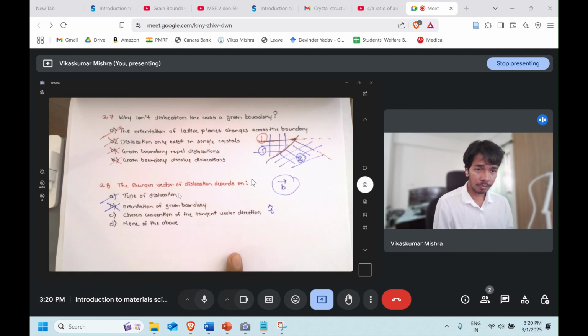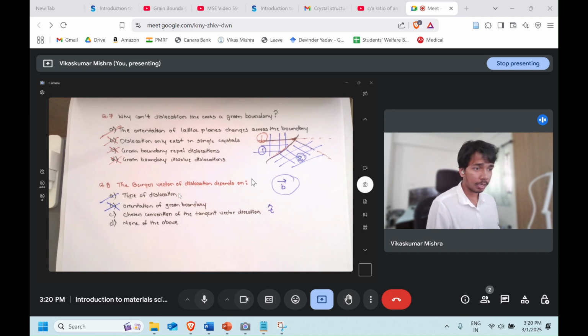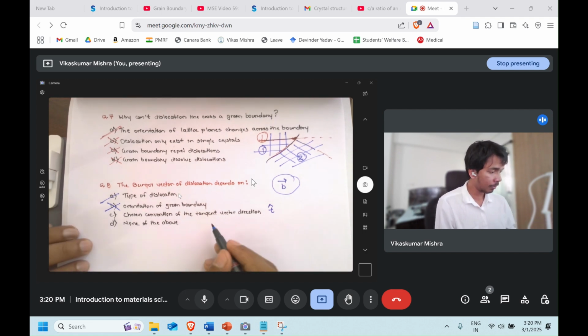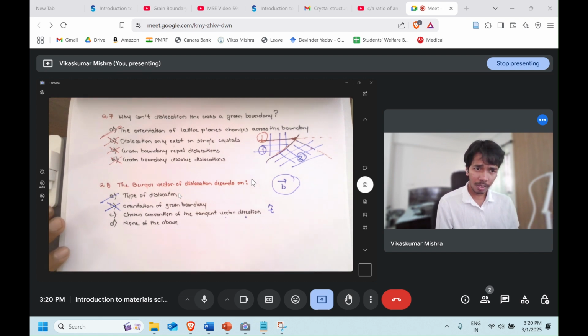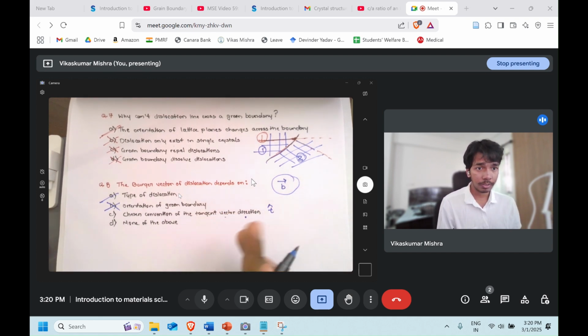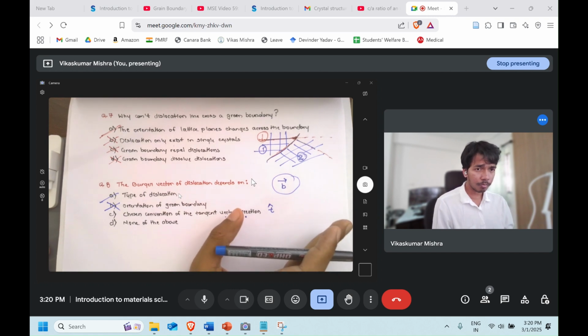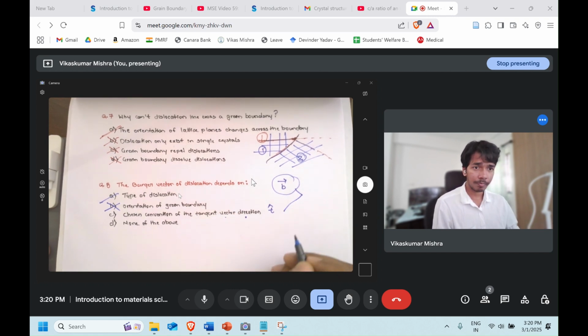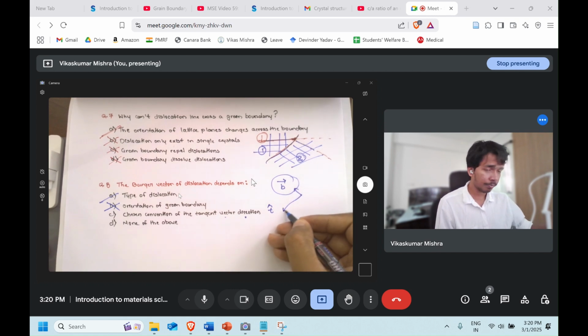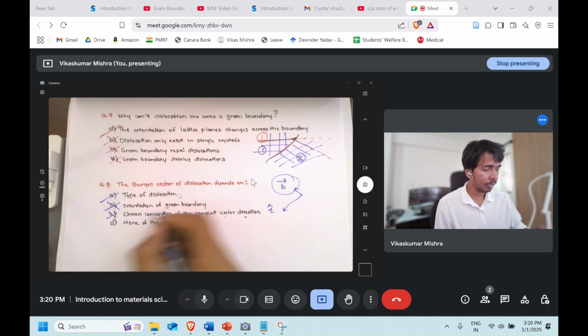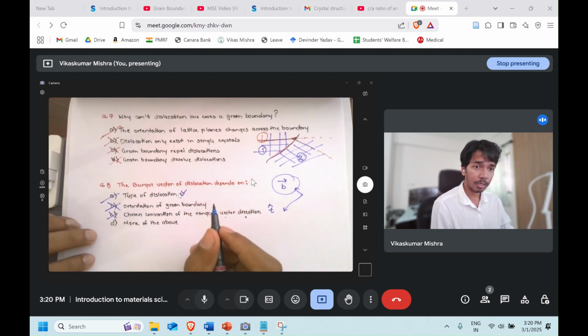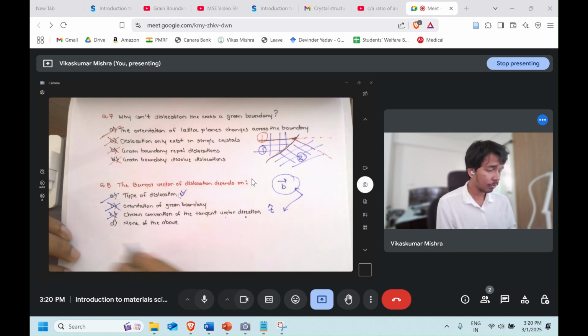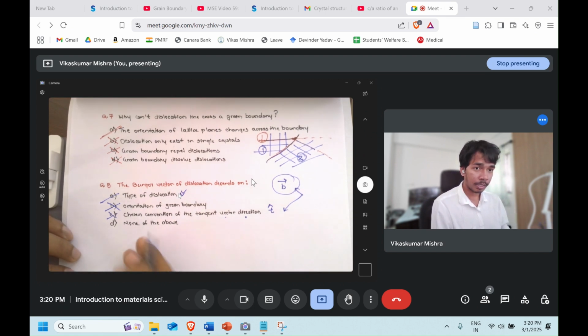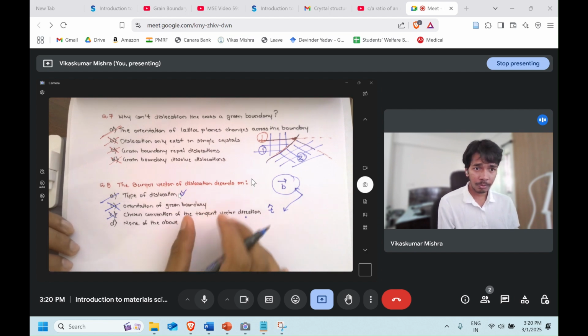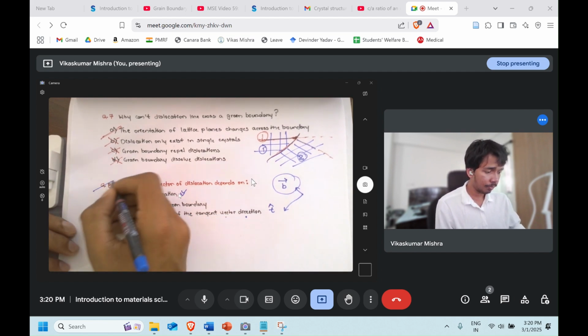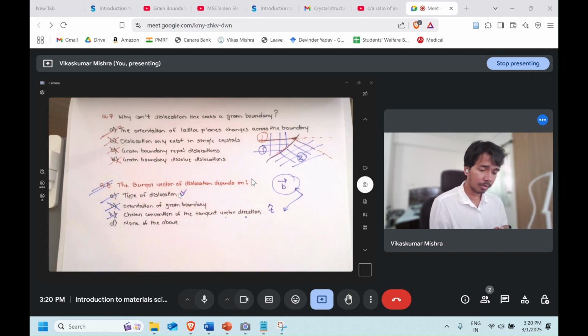So the orientation of the grain boundary is not the one which is going to decide the Burgers vector. The chosen convention of the tangent vector direction: no. A tangent vector direction will always be along the dislocation line, so there is no relation between B and T, the Burgers vector and the tangent vector. This is incorrect. The only correct answer is the type of dislocation. It will also depend upon the crystal structure. So instead of none of the above, I could have written that it will depend on the crystal structure of the material. So that would also be a correct option.